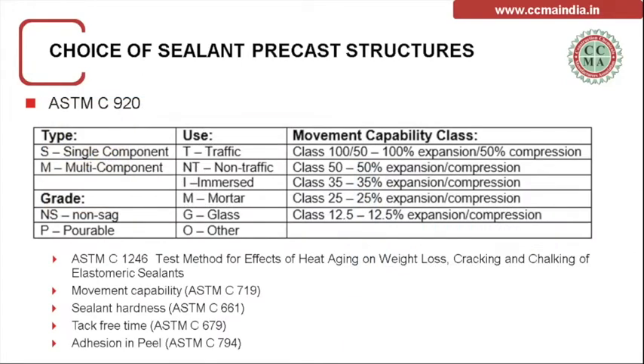They will specify this with the standards, which qualifies ASTM C920, as we are all aware. It covers single component or multiple component, and whether they are using it in facade, sag or non-sag grade, all those things will be chosen exactly as per ASTM C920. And then mainly they will qualify in ASTM C1246 for durability, heat aging, weight loss or chalking when exposed to UV. This is what they qualify. Rest all is very standard. They see the hardness, movement accommodation capability (MAF), and tack-free time.